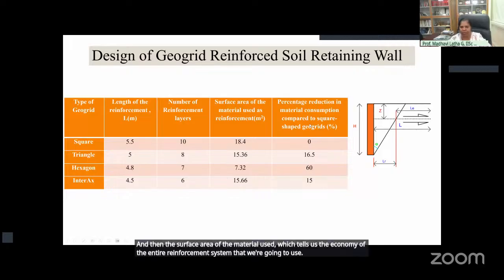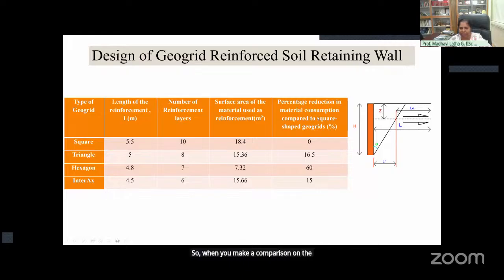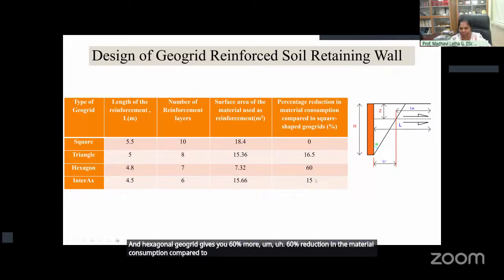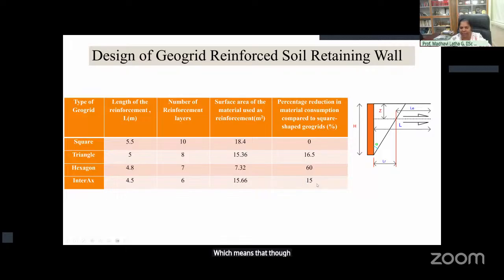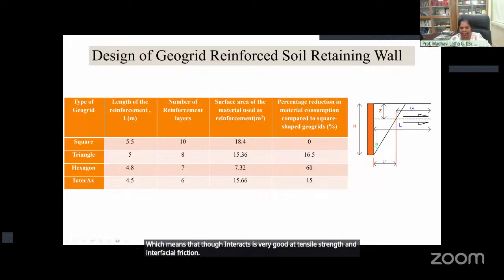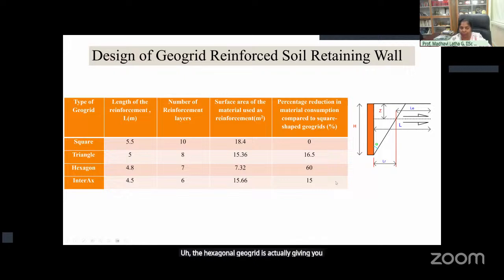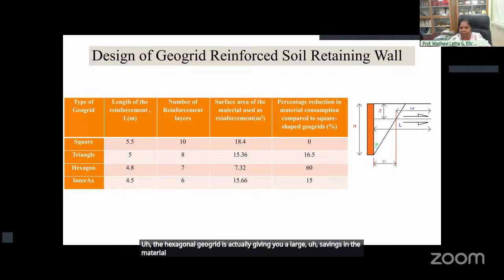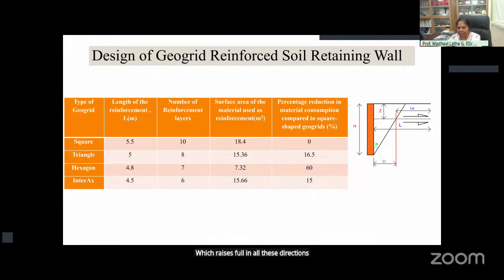which tells us the economy of the entire reinforcement system that we're going to use. So when you compare the percentage reduction in material consumption compared to square geogrids, for the square there won't be any material reduction because it is a square to square comparison. In the case of triangular geogrids, you have 16.5% saving in material, and the hexagonal geogrid gives you 60% reduction in material consumption compared to Interax, which gives you 15. This means that though Interax is very good at tensile strength and interfacial friction, the hexagonal geogrid is actually giving you large savings in material because the arrangement of its ribs in 6 different directions resists pull in all these directions with least material.